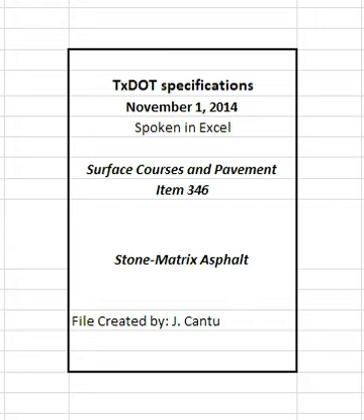4.9.2.4.4 Fibers. Suspend production and shipment of the mixture if fiber content varies from the design target value by more than 10% on 2 consecutive tests.